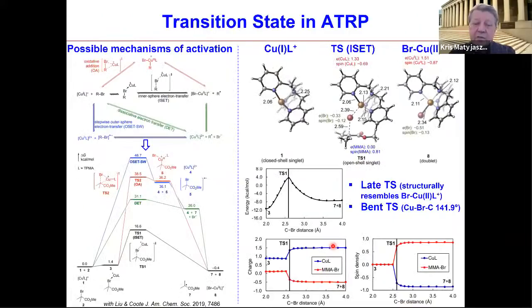So let me go now to the essence of ATRP. Atom transfer can happen in a couple of different ways. Here you can see that the preferred process is inner sphere electron transfer, where bromine bridges carbon with copper, forms radicals, and oxidizes copper to the Cu(II) species. This is one possibility. There is also outer sphere electron transfer, forming a radical anion, which would then dissociate to radical and anion. Or you can have a concerted process, dissociative electron transfer via a so-called sticky electron transfer process. And finally, you can have oxidative addition passing through copper-free intermediates.